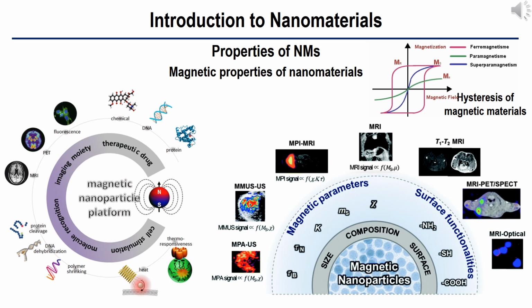One can obtain magnetic nanoparticles of palladium, of platinum, and the surprising case of gold, which is diamagnetic in bulk, from non-magnetic bulk materials. In the case of platinum and palladium, the ferromagnetism arises from the structural changes associated with size effects. However, gold nanoparticles become ferromagnetic when they are capped with appropriate molecules.